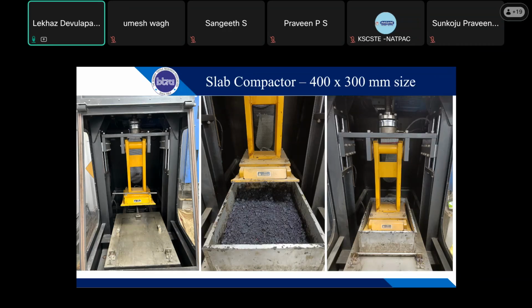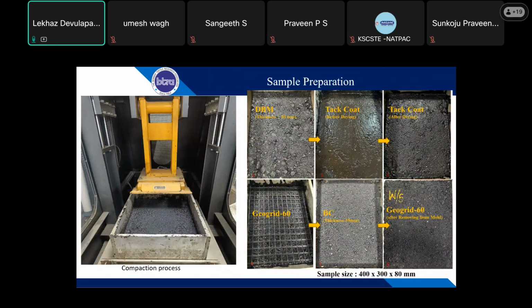Once that is done, then we will prepare the sample. This is the sample preparation process. First we prepared the DBM of 50 mm thickness, and after the DBM was prepared, we waited overnight so that it cooled down, and then we applied a tack coat. After applying the tack coat, we left it for drying, and the geogrid is placed on the tack coat. Then we placed the BC, which we had already prepared, and compacted it, and then the slab is removed from the mold. The slab size was 400 by 300 by 80 mm thick, which is what we usually create for this research.